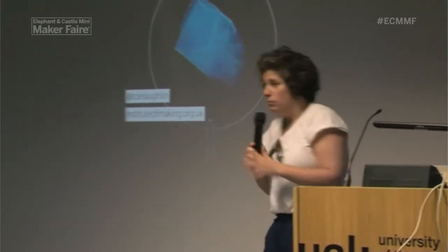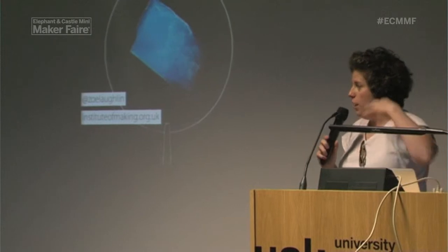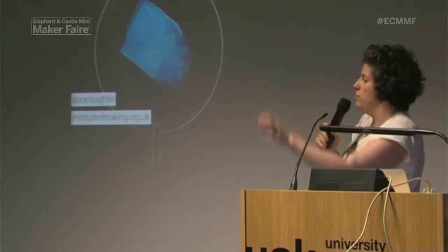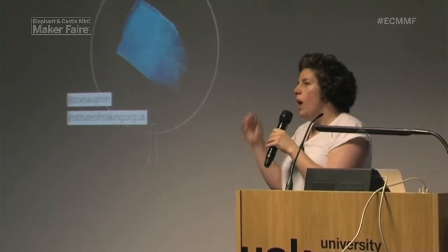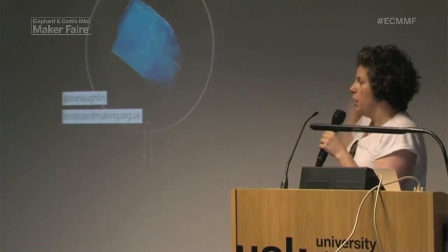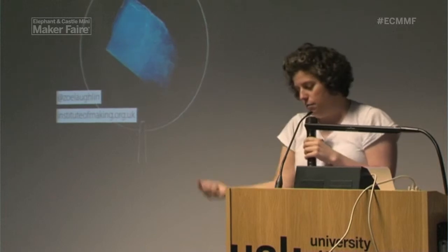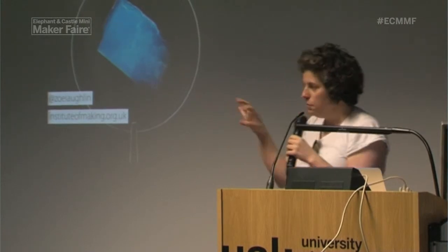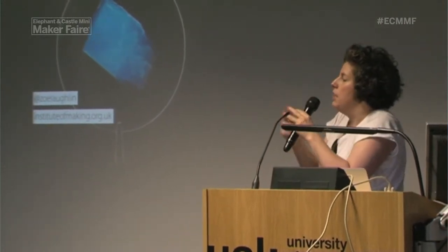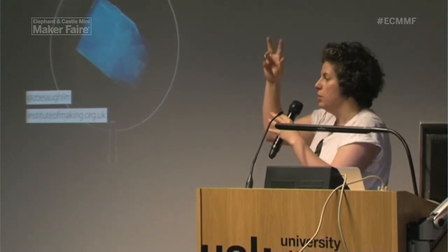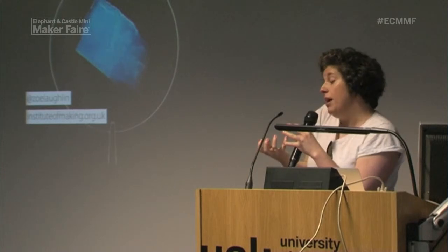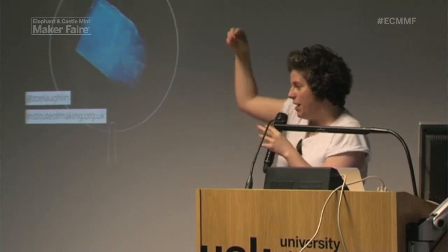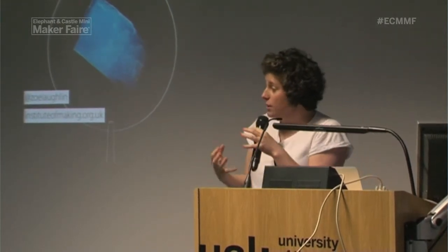What's it good for? NASA used it to catch stardust. They took it up in a satellite, I think, and then they stuck it out behind a comet, and all these bits of dust that were flying off the comet lodged in it. When things hit things in space, they're going incredibly fast, and you had two options. The dust would either hit something and the dust explodes, or the dust damages the thing. In this case, because you've got those tiny pores, each one can act like a crumple zone, and each individual pore can explode and catch that dust, but it doesn't damage the rest of the material, so the homogeneity of the material isn't affected. Then these dust particles could be brought down to Earth and examined.